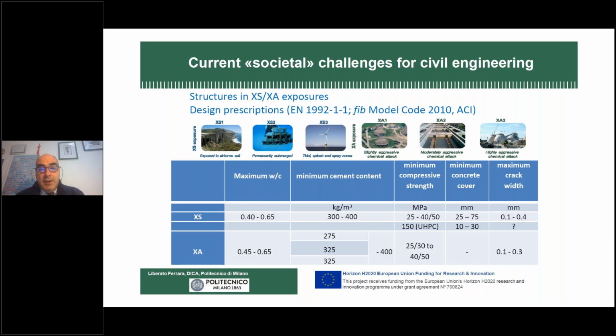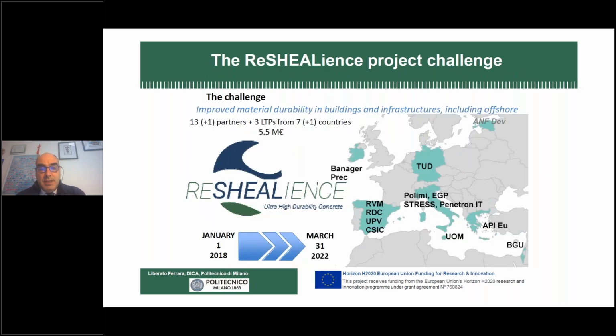So this was the scenario, and when we go to the design codes, we actually find only prescriptions based on minimum cement content, maximum water cement ratio, and so on. But these prescriptions, if we go to modern concrete, high performance concrete, or even ultra high performance concrete, are automatically guaranteed. So we do not really have a performance-based durability design framework, which can help us also in promoting the innovation in this sector.